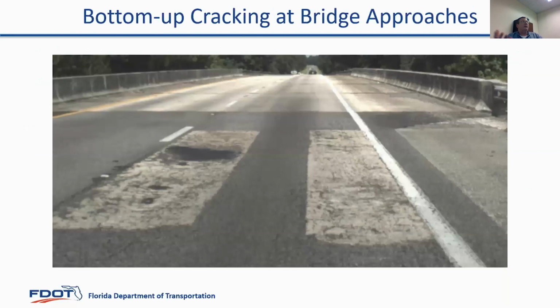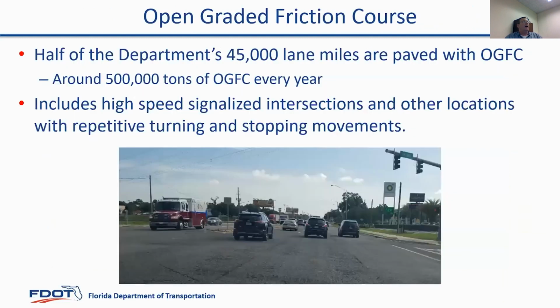And then here's some places where we do get bottom-up cracking. A lot of times on bridge approaches at interstates, where the interstate was originally built at about 5 inches thick. Over time, we've built that up. It's 10 inches thick, but you got to tie back down into those bridges. You see a lot of fatigue cracking bottom up right at the bridge approaches. And this is a great place to use high polymer binder to address that. So the next distress we use high polymer binder for is in open graded friction courses where we've got a history of raveling or where there's a lot of repetitive stopping and turning movements.